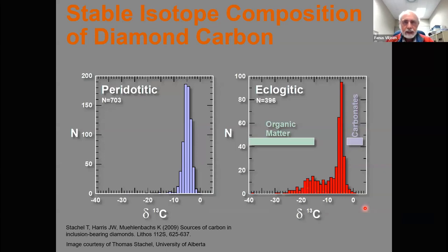Now, because diamond is essentially 99% carbon, you can look at the carbon by burning the diamond and putting that gas then through a mass spectrometer to determine the carbon-13, carbon-12 isotopic composition of diamond. If we do this for peridotitic diamonds, you find that the carbon isotopic composition is comparatively restricted. If we do this for eclogitic diamonds, you find that the carbon isotopic composition is of quite a large range. And some of this carbon isotopic composition corresponds to or overlaps with the carbon isotopic composition of organic matter. And some of this range in carbon isotopic composition also corresponds to the carbon isotopic composition of carbonates.